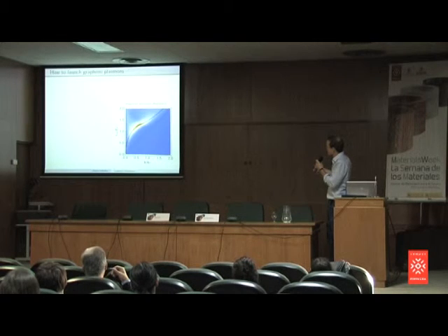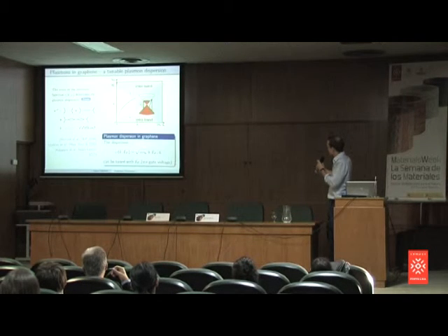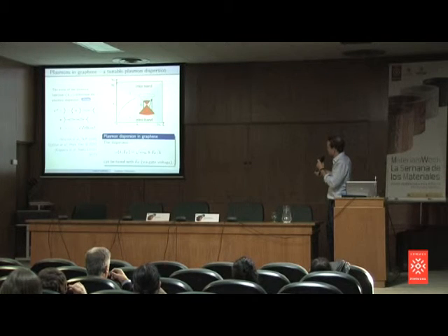What happens up here? We open a kind of decay channel at these energies. You can make interband transitions here, and then the plasmon decays. That's why the curve stops here. But okay, down here it's stable. And this dispersion just looks like this. Frequency of the plasmon goes like the square root of the wave vector, and that's not spectacular.